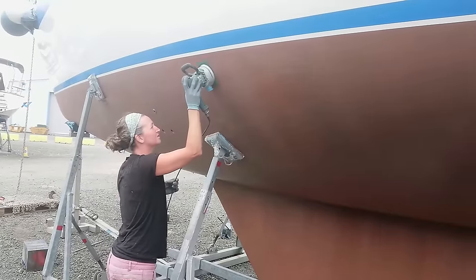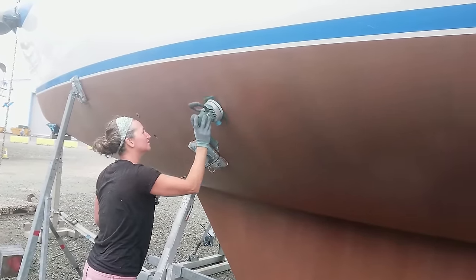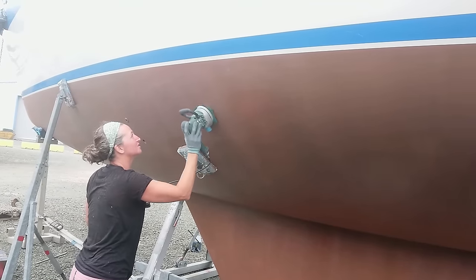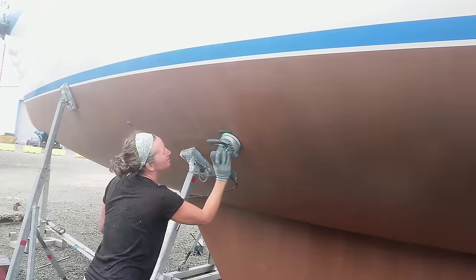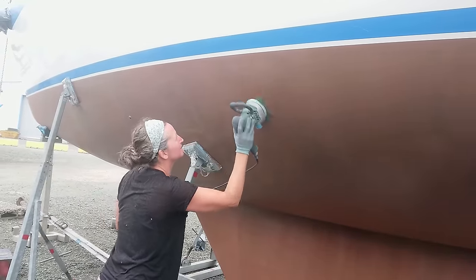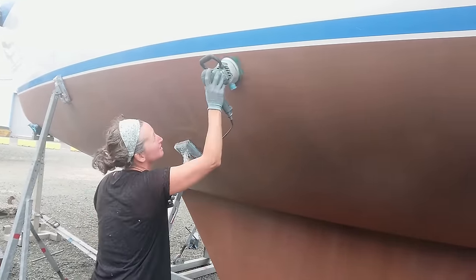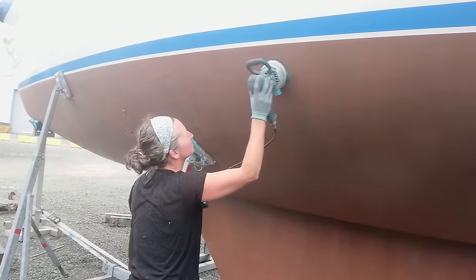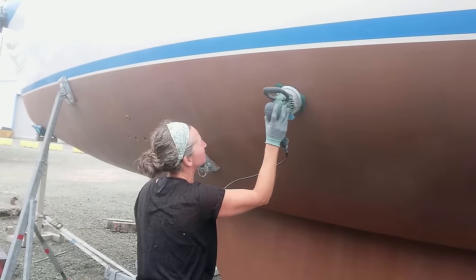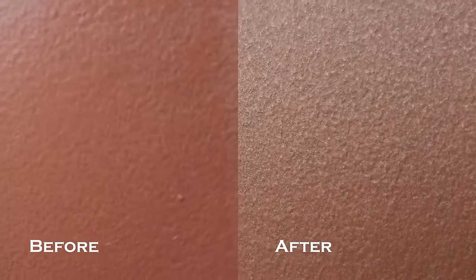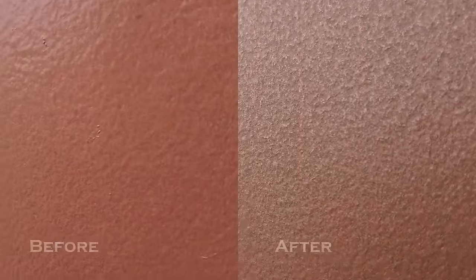So once the copper coat had fully hardened, we abraded over the whole thing with a Scotch-Brite pad attached to the orbital sander. Once the resin is removed, it leaves a material percentage of 80% copper on the surface of the hull. And it's this copper that, once exposed and in the water, quickly oxidizes and acts as a very effective antifouling. You can see the difference in colour here once we've exposed the copper underneath that surface layer of epoxy.